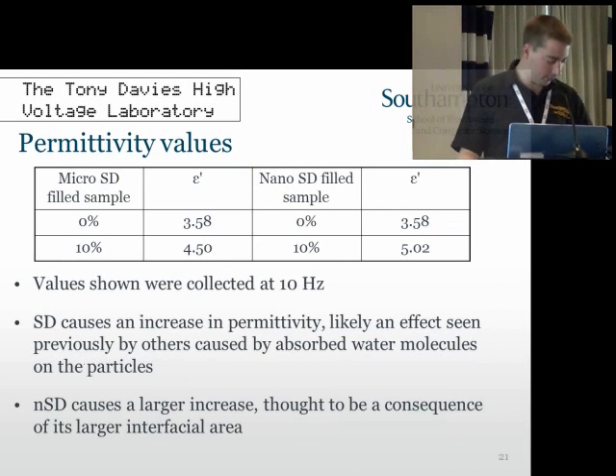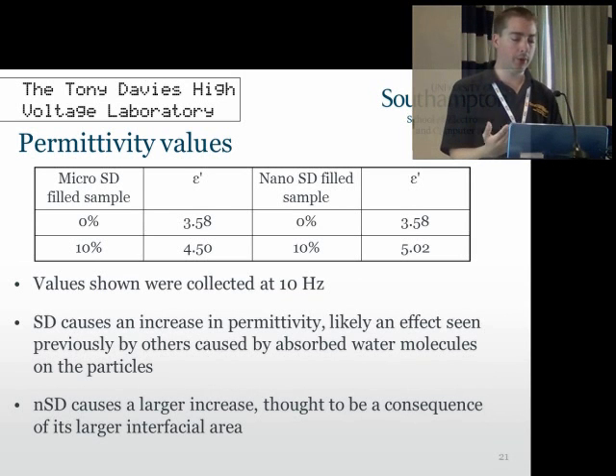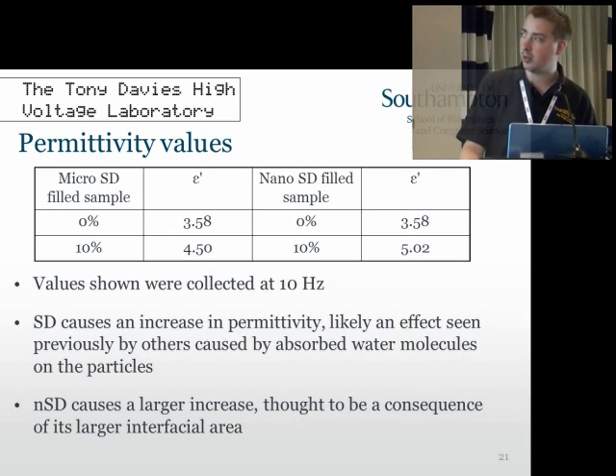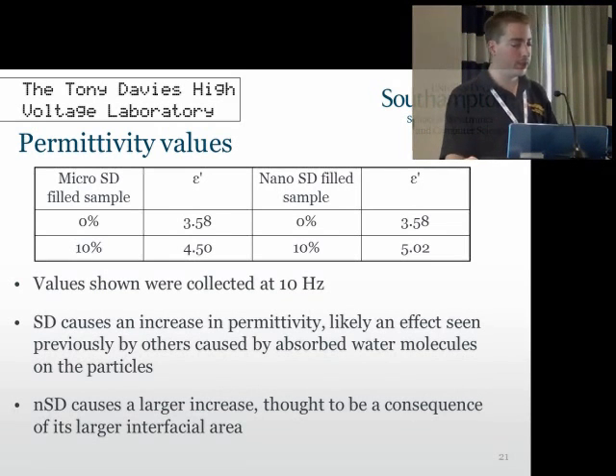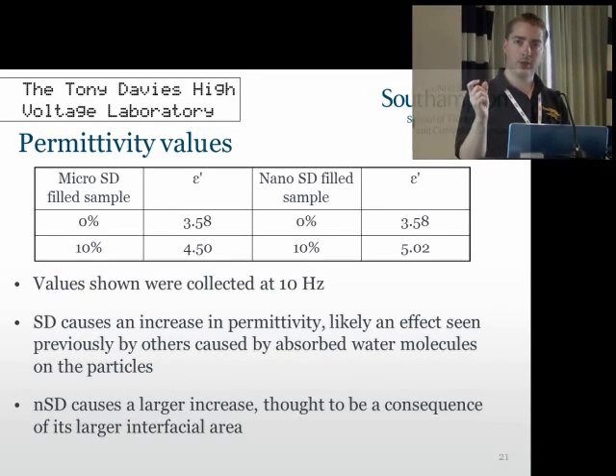Having a quick look at the permittivity values, we did notice that these are all taken at 10 Hertz, by the way. We did notice that the permittivity of the unfilled system was approximately what we expected for an epoxy system. However, the permittivity for both of the filled systems, the micro and the nano, has actually shown quite a large increase. Now this wasn't expected because the silica has a permittivity around the same as the epoxy. So something's obviously not right here. We had a look at this, and we've decided that what's likely happened is that the filler has actually collected water on the surface. So on the surface of the micro and the nano spheres, we're collecting a layer of water.